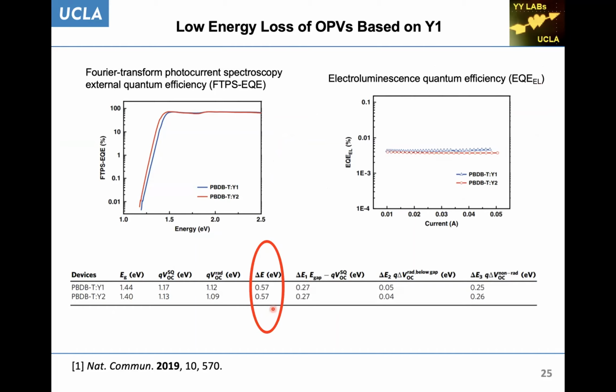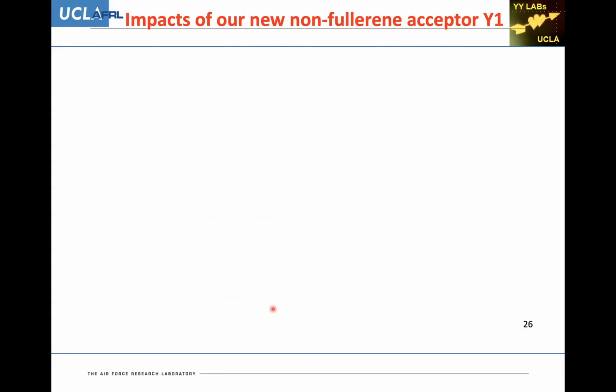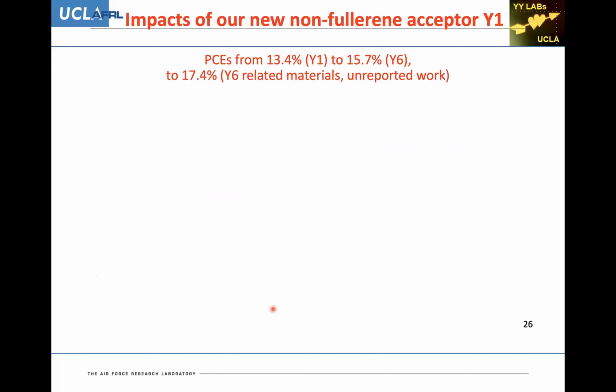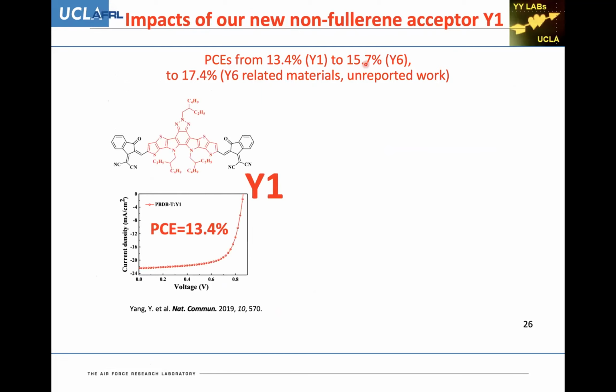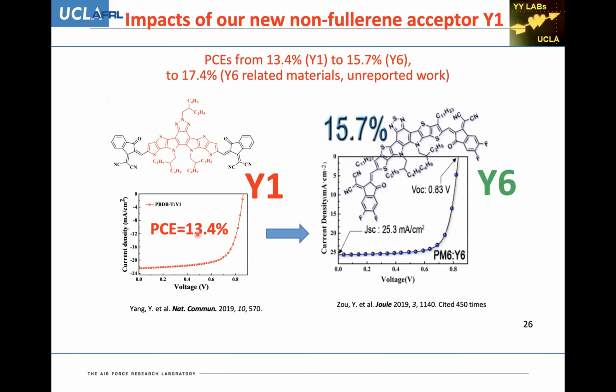So we are able to use the new material to cut down the VOC loss. That has not been demonstrated in organic solar cells. Organic solar cells usually have a loss of like 0.8 eV or 1 volt. That is sometimes very high. The exciton binding energy was very strong. Anyway, the impact of our acceptor Y1 is that the PCE went from 13% with Y1 to 15% with Y6, all in 2019. So I just want to tell you that those are the works in my group.